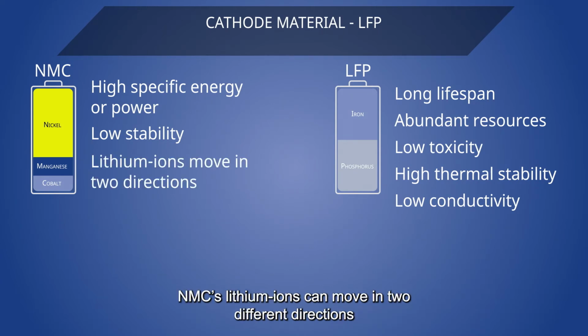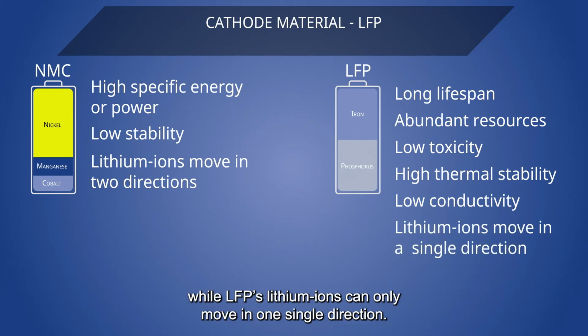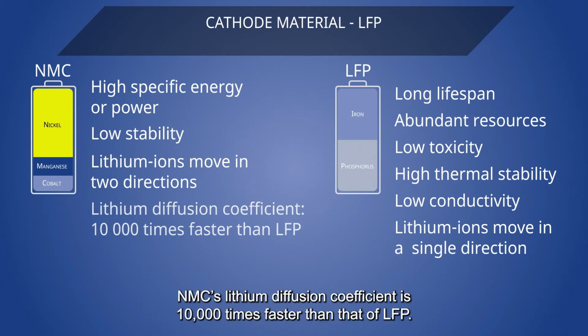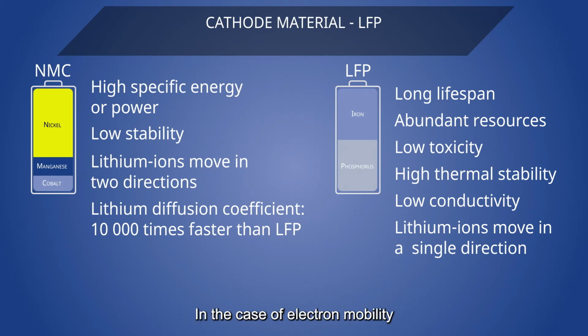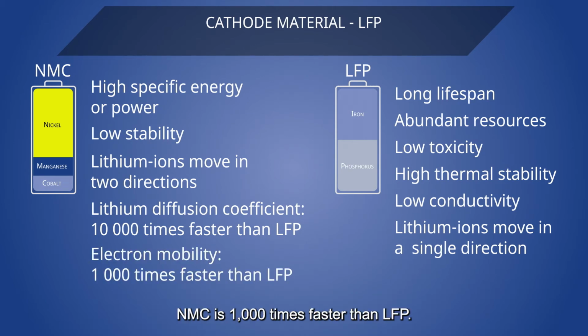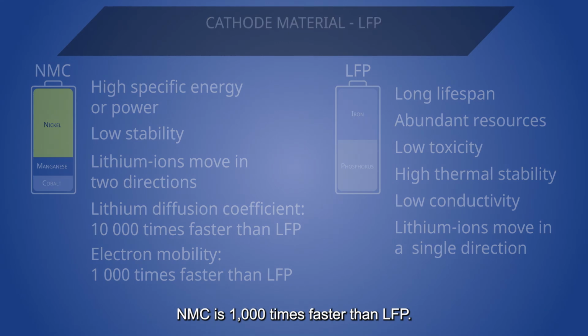NMC's lithium ions can move in two different directions, while LFP's lithium ions can only move in one single direction. NMC's lithium diffusion coefficient is 10,000 times faster than that of LFP. In the case of electron mobility, NMC is 1,000 times faster than LFP.